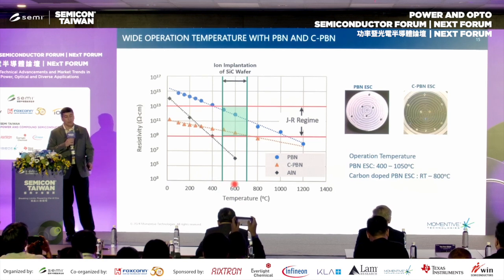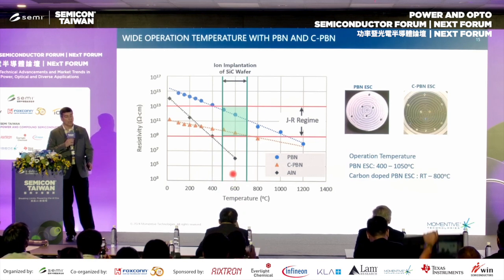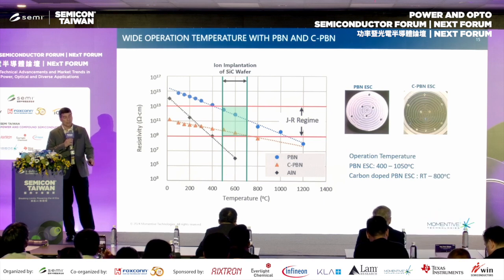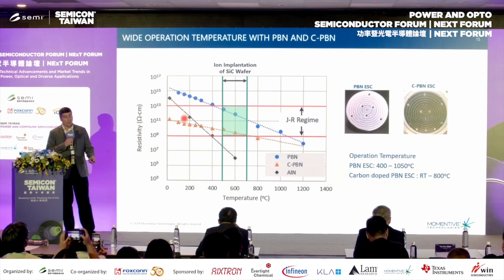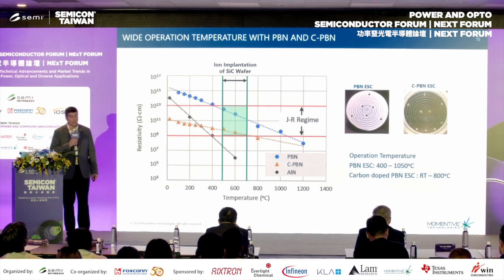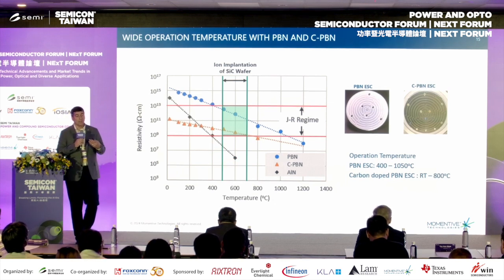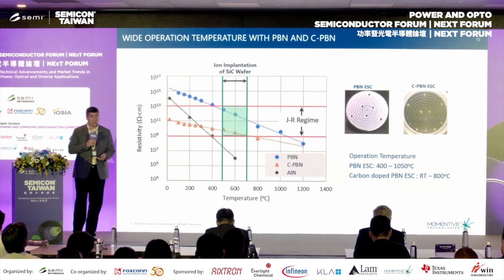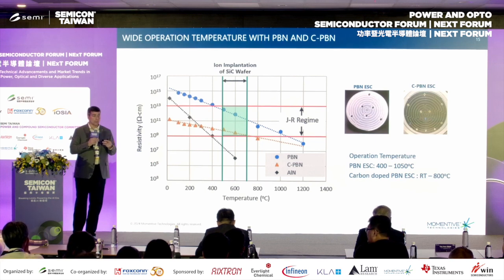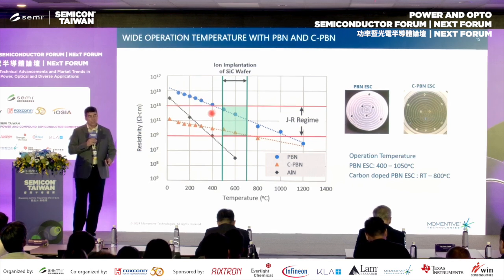So you're up here in the sort of 500 to 700 degrees C range to do proper ion implantation. Competitive materials like AlN, right, would drop off in resistivity as you get to those temperatures. The resistivity is important because if you're trying to make an electrostatic, a JR, particularly electrostatic chuck, you need to tailor the resistance of that top coat to make sure you get good chucking forces, right? And so our PBN coatings have a very high intrinsic resistivity, and then they can be doped to achieve a lower resistivity. Of course, we can control this doping, and that allows us to sit nicely within that resistance band that you need for JR chucking.